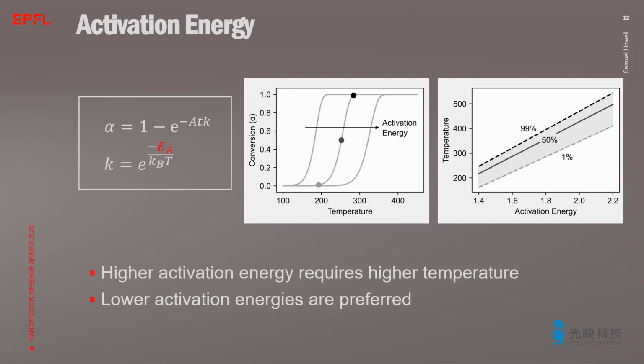Another parameter is the activation energy of the reaction. The higher the activation energy, the more heat is necessary to induce the reaction, and hence the higher the temperature needed to complete the reaction, as can be seen in the figure. In the graph, one can see that the reaction curve shifts towards higher temperatures with increasing activation energy. The temperature necessary for a reaction increases linearly with the activation energy, as can be seen in the right graph. As a general rule, reactions with low activation energies are preferred for thermal scanning probe lithography.